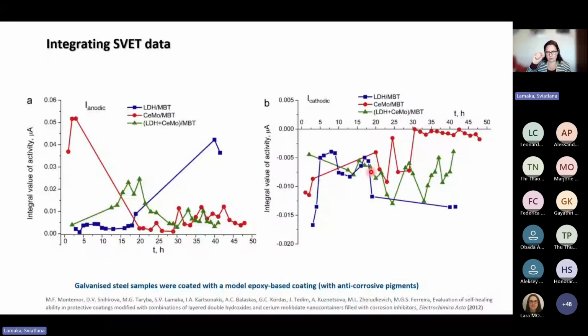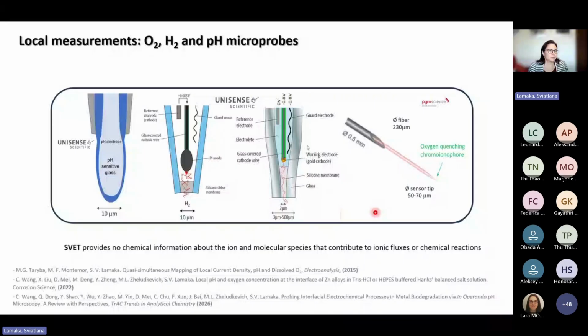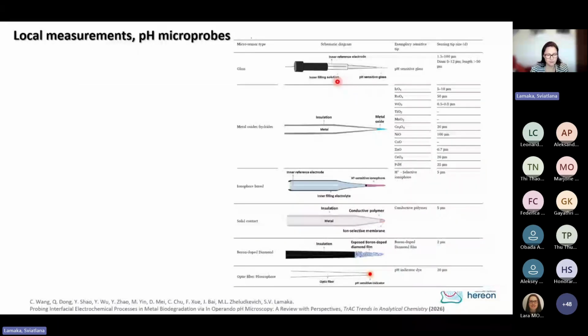at least, because we can fully rely on the values and don't think about what might have happened, was there a drift of potential, and that's what we typically observed for glass capillary microelectrodes with ion selective ionophore in the tip. They are unfortunately prone to some potential drift, and this complicates the interpretation. Now, the disadvantages of these glass electrodes are that they are still very fragile because the tip is very small. Well, small, depending on what you're comparing to: the diameter is around 10 micrometers, but the length is around 50 micrometers. So if you really want to do point analysis, perhaps ionophore-based microelectrodes is still an option, because here we're talking about a diameter of the orifice of 2-3 micrometers, so it's a smaller tip size. But nevertheless, the biggest advantage is very, very stable potential.